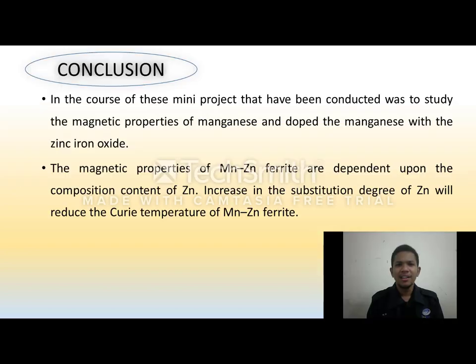Thank you. The purpose of this mini project that has been conducted was to study the magnetic properties of manganese, and to dope the manganese with zinc iron oxide. The magnetic properties of manganese zinc ferrite are dependent upon the composition content of zinc. Increase in the substitution degree of zinc will reduce the Curie temperature of manganese zinc ferrite. The particle magnetization increases with the increase of the composition content of zinc for smaller atoms, but decreases with further increase of the composition content of zinc above x equals 0.6.